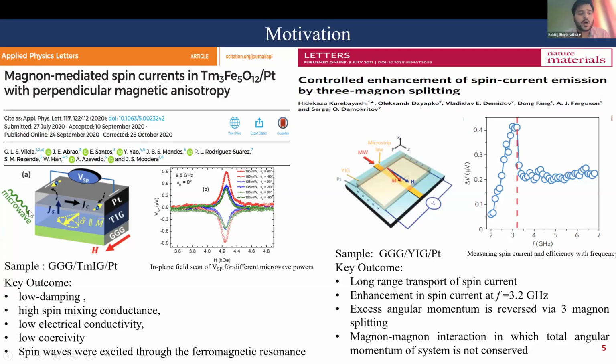As you can see here, on applying the microwave frequency in the presence of an external field, the TMIG magnetization transfers its spin polarization towards the heavy metal side, producing a charge current across the edges, which is measured using the nanovoltmeter as the spin pumping voltage, V_SP, because of the inverse spin Hall effect. Parallelly, you can also see this plot where there is an increase in the spin pumping voltage with the increase in power, which is the significant signature of the production of spin pumping voltage with the ISHE.